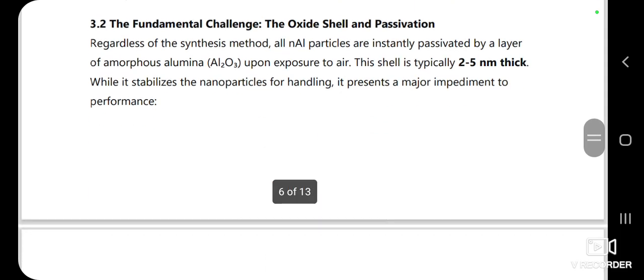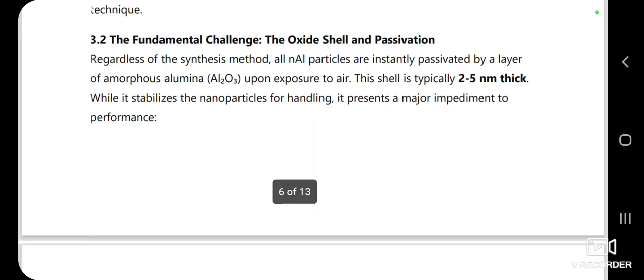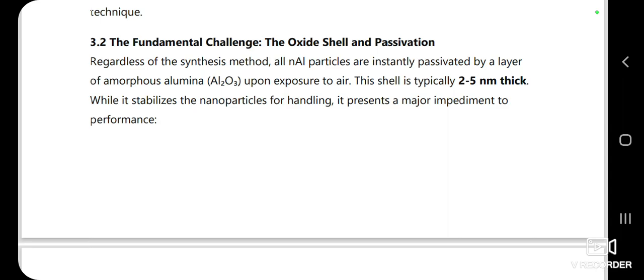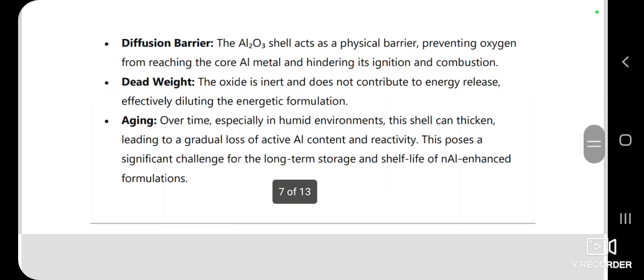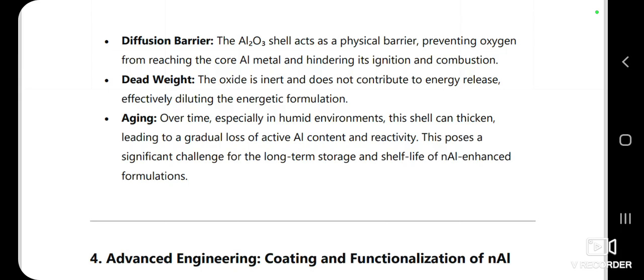Now we study a fundamental challenge that we face, the oxide shell and passivation. The moment nano aluminium hits air, it instantly grows a 2 to 5 nanometer thick shell of aluminium oxide. Think of it as a nano suit of armor. While this lets us handle the particles, it causes three big problems in their performance. The first is the diffusion barrier problem. The aluminium oxide shell acts as a physical barrier, preventing oxygen from reaching the core of aluminium metal and hindering its ignition and combustion.